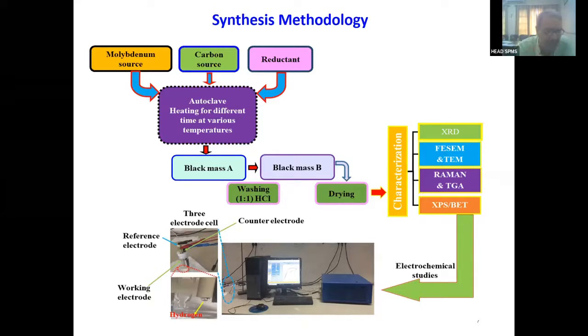That oxygen has to be removed. So what we are going to do is purge some argon or some other inert gases so that the oxygen may come out. Even then, despite doing all these things, we realized that there is some leftover oxygen which is not desirable, because we want to convert the oxides to carbides here.